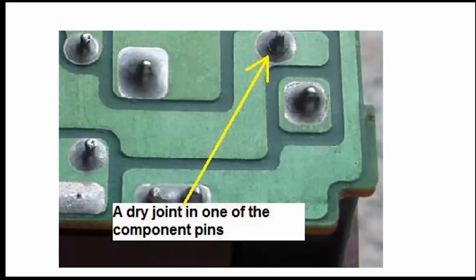Now there's a dry joint there, and you can see the rest of the joints on that board are shiny. They look like little volcanoes, smooth-sided. That one at the top is grey, it's not as shiny, and you can actually see the cracking occurring halfway down the slope of the little volcano. What usually causes a dry joint is one or two things, typically temperature shock. That occurs either because somebody blows on the joint, or a draft hits the joint, or whatever, but the joint gets cold. But also you can get it from mechanical shock.